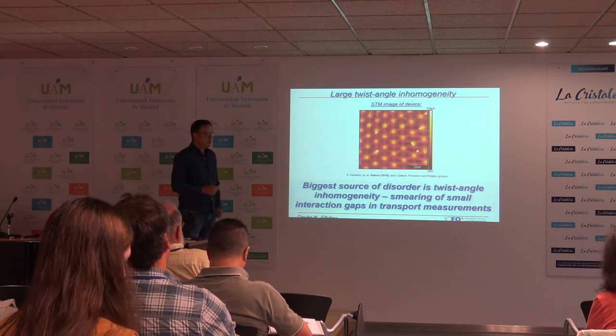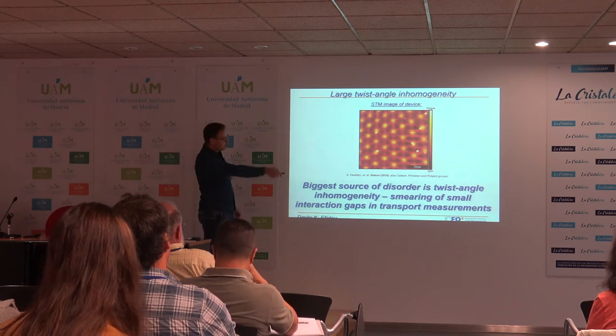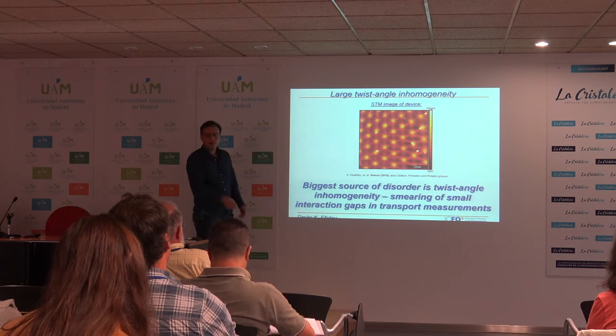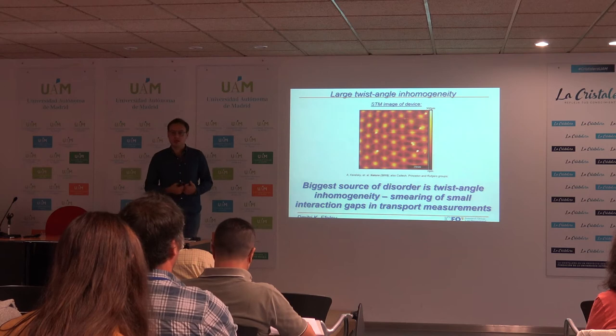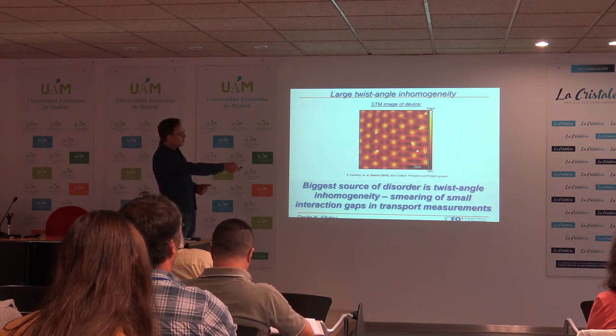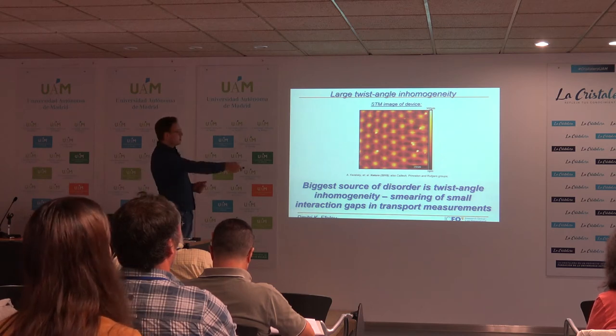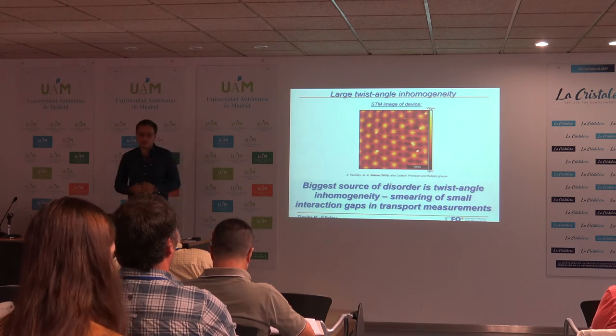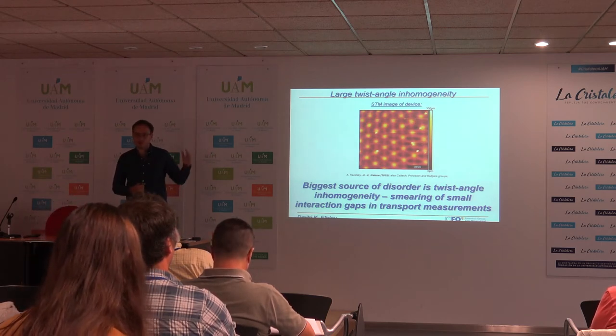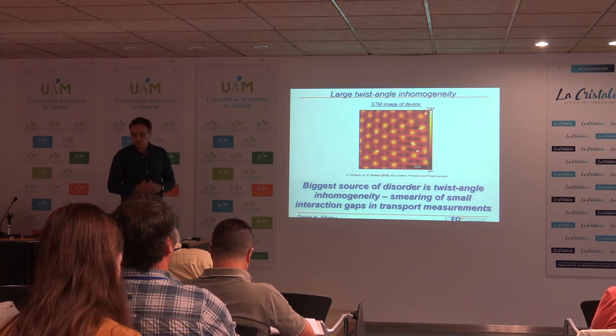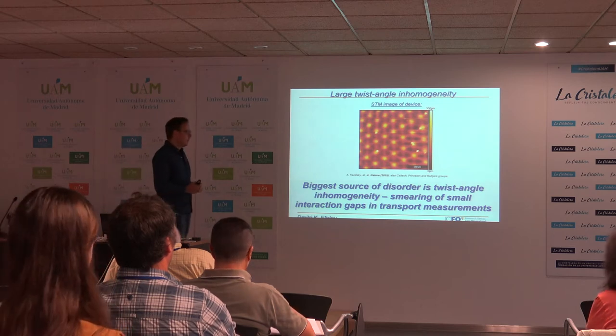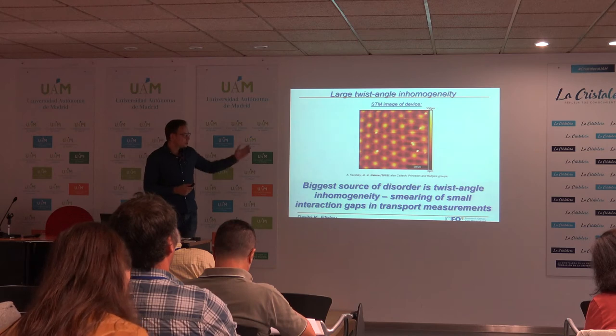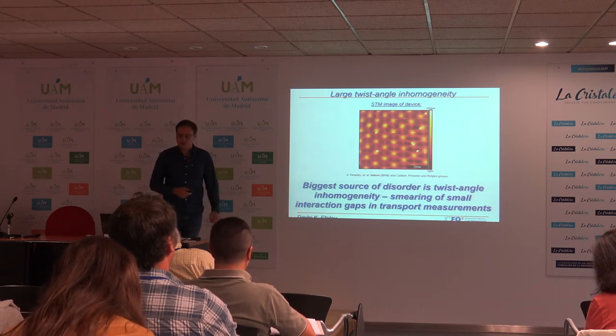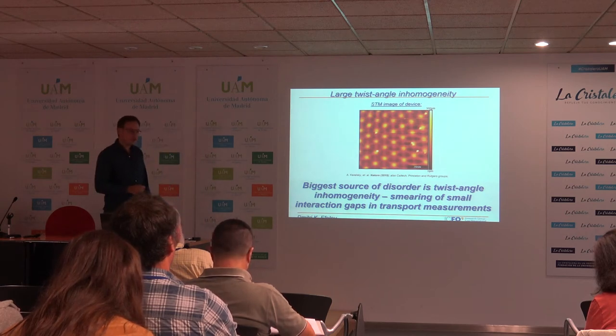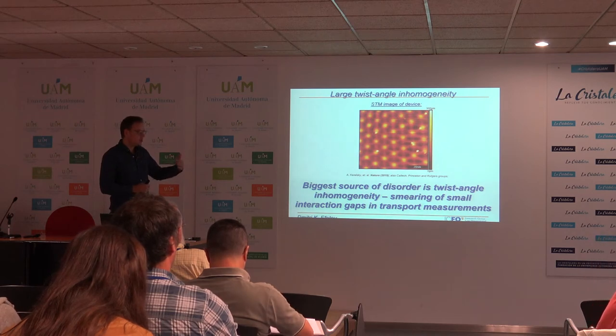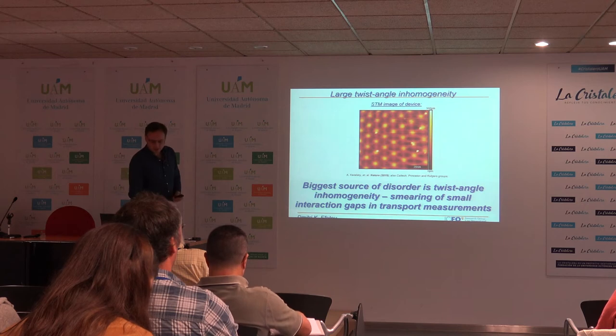But what you can also see here is that this lattice is by far not perfect. If you look at the lattice constant at the bottom corner, or the lattice constant at the top corner, you can see that it's adiabatically deformed. So just within a 100 nanometer device, you can get twist angle changes over several tenths of a degree. This is similar to what Pablo was showing about the scanning SQUID experiments, where they can map out the twist angle by Landau level spectroscopy. In principle, such disorder also affects the transport properties. So it would be a big challenge to see what in our transport results is intrinsic and what is actually disorder driven.